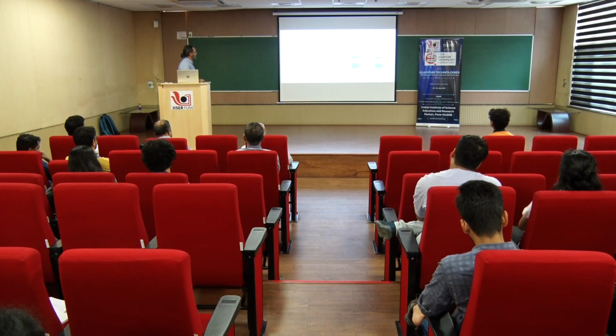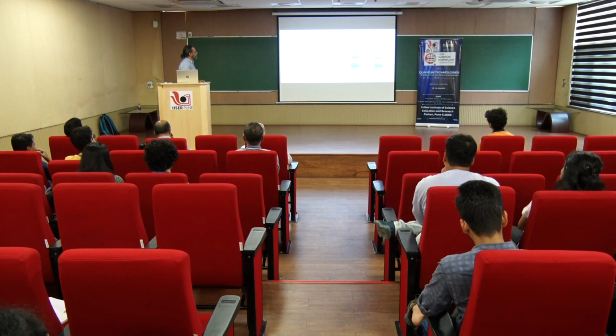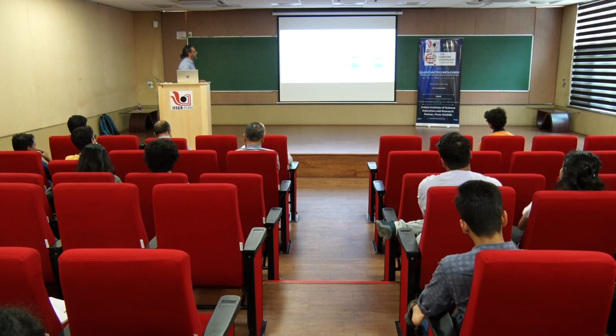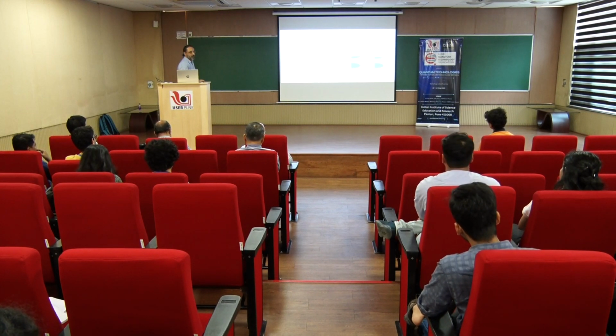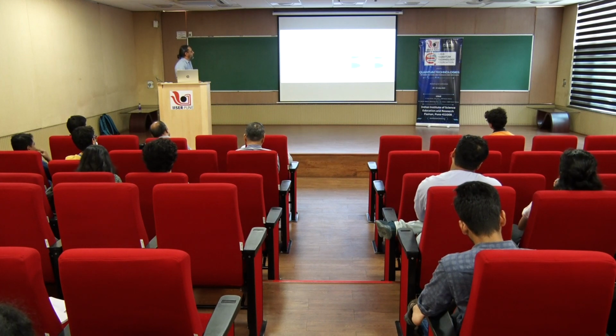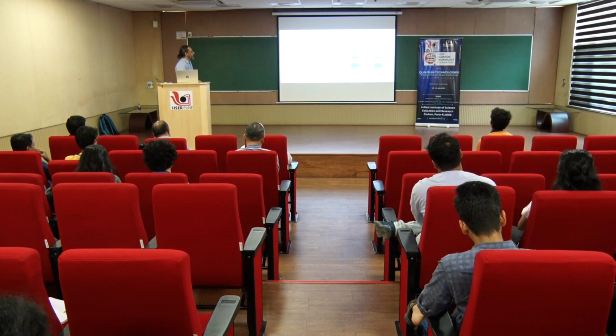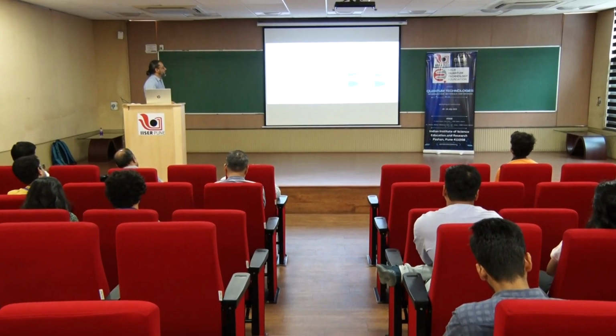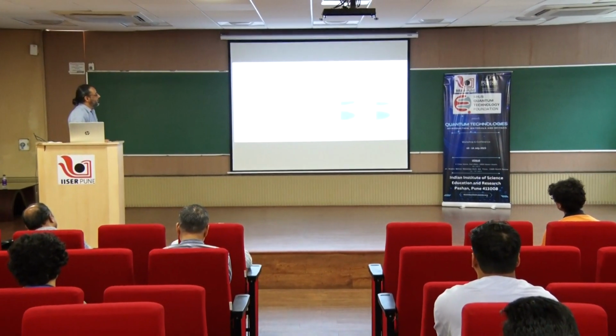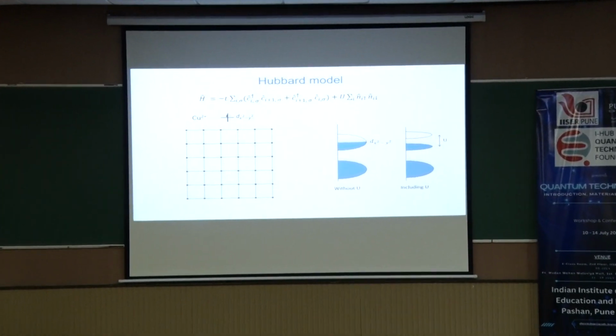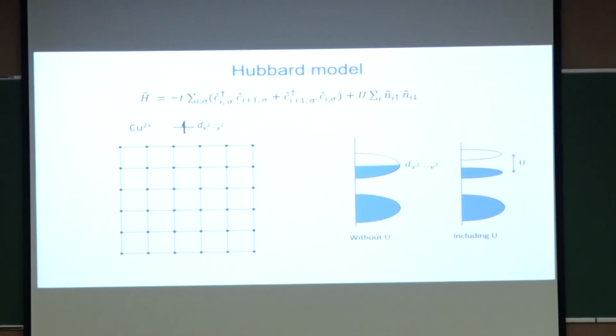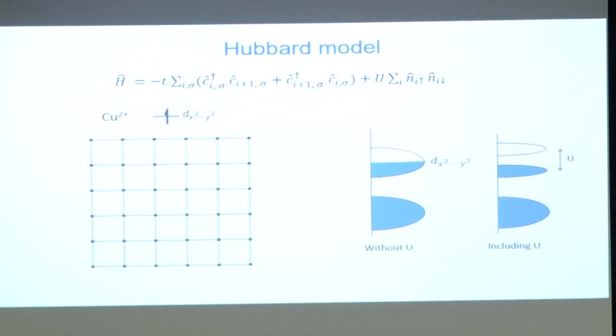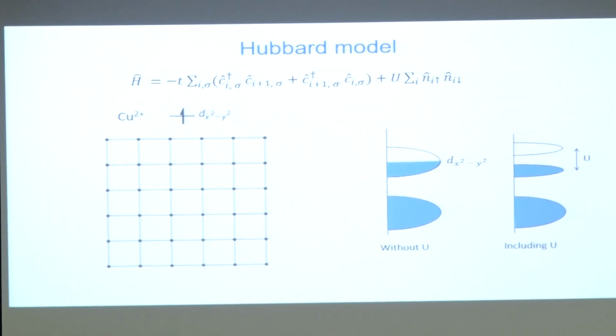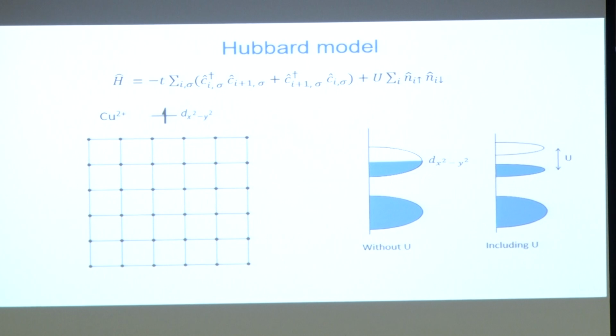So, basically this d orbital x square minus y square will split into these two bands. This is known as the lower Hubbard band and this one is the upper Hubbard band. The lower Hubbard band is completely filled because this dx square minus y square can take 2 electrons per site, and now you have 1 electron per site here, and this is the second half of it, and these are separated by the energy U. It was very nicely explained in the previous talk that the competition between U and T can give rise to a metal to insulator transition.